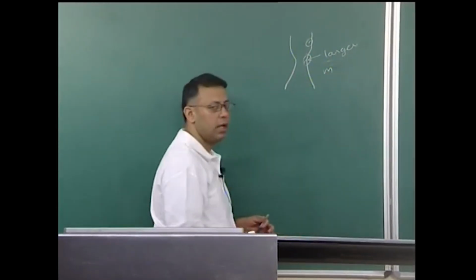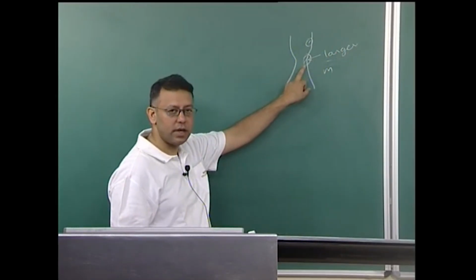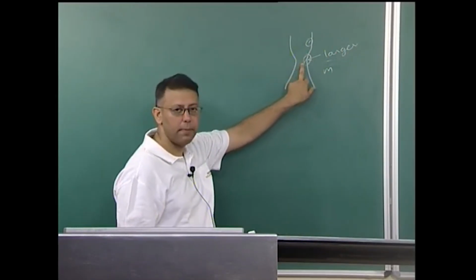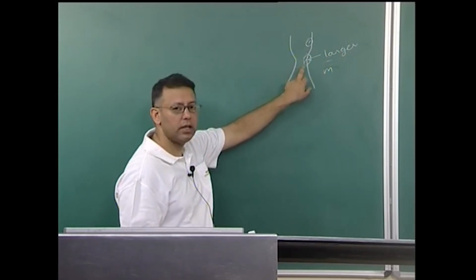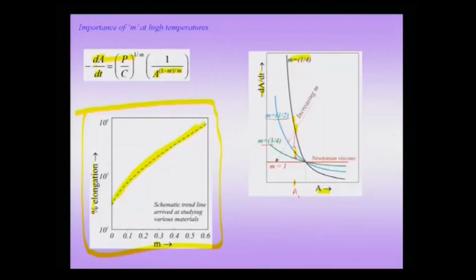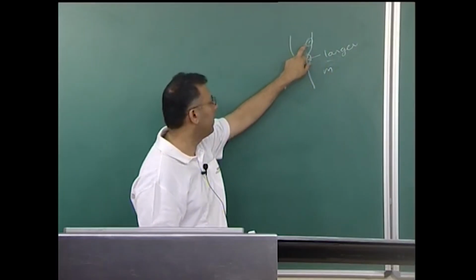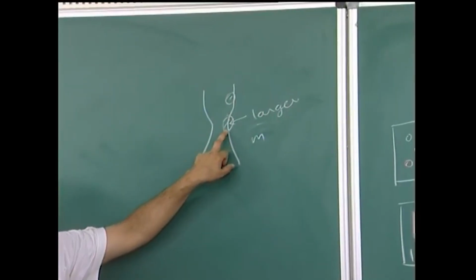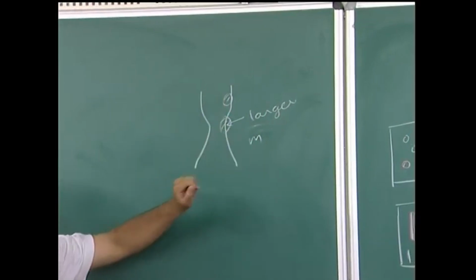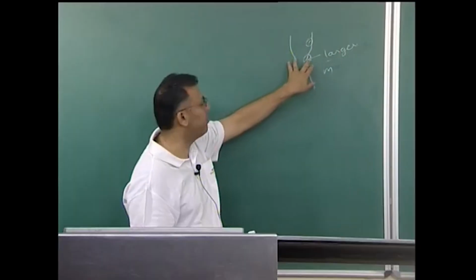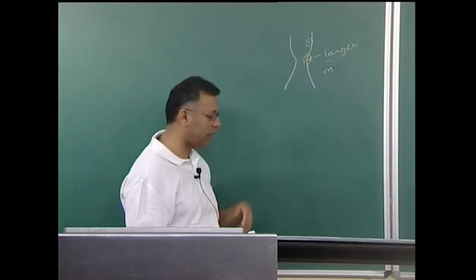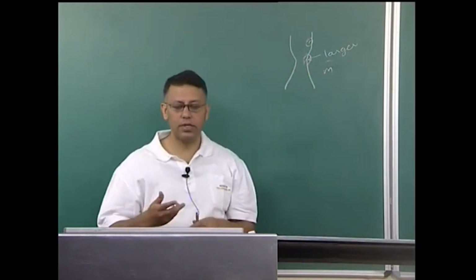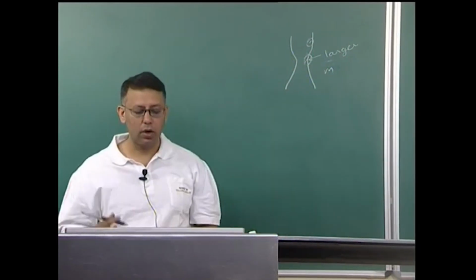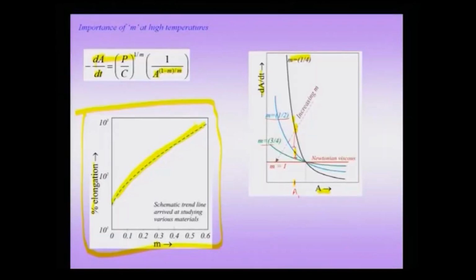What I told you for n at low temperatures can now be thought of as m for high temperatures. That means, if necking is going to take place, there is a reduction in area, and there is a dA by dt term here. Since there is a larger reduction here, the dA by dt here is going to be larger than the dA by dt where there is smaller reduction in area. This implies this region is going to get harder with respect to that region if m has a high value, which also implies that the necking would spread to other regions, and the deformation will not be localized to the region where the original reduction in area took place. That means now I will get longer elongation, and therefore I can understand a schematic trend line which has been drawn here for these materials.